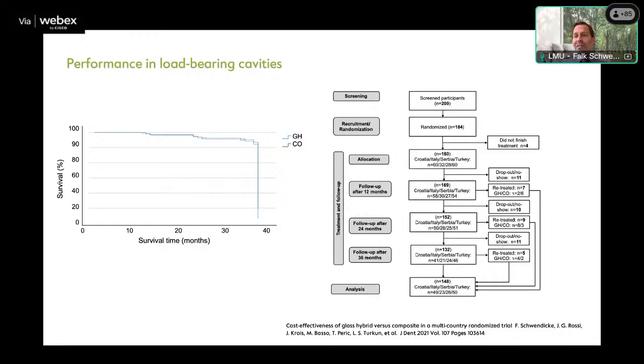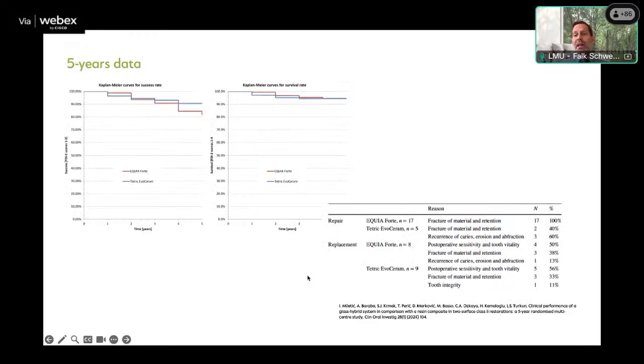And what is most notable is there's basically no difference. These lines largely overlap, so the annual failure rates over the 3-year periods were nearly exactly the same between the glass ionomers and the composites, which was really astonishing at that time, particularly coming from 4 different independent groups in a trial with over 300 cavities, which is a rather large trial, at least in dentistry.